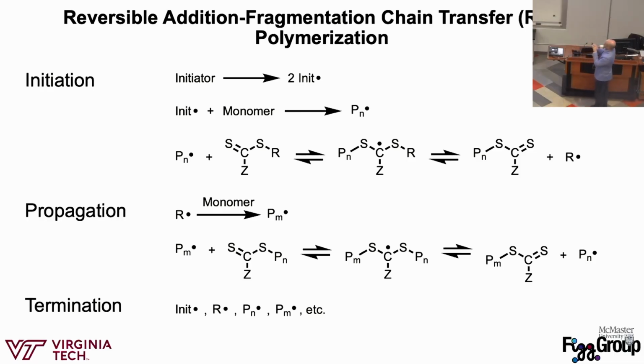So what we want is for this prepolymer that was initiated by the initiator to react across this carbon-sulfur bond to give us this intermediate. We're going to call this a chain transfer event. And then these RAFT agents are specifically designed to fragment off the R group in this pre-initiation stage. So we design it so the equilibrium goes this way, and this R dot is more stable than this Pn dot. Just to ground you in some stoichiometry, usually with initiators, we want about 1% relative to chain transfer agent. So that means 99% of our chains are going to be started from this R dot, and only a small percentage are going to be started from this initiation pathway.